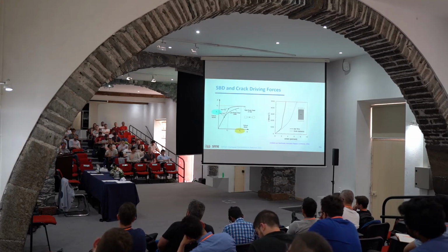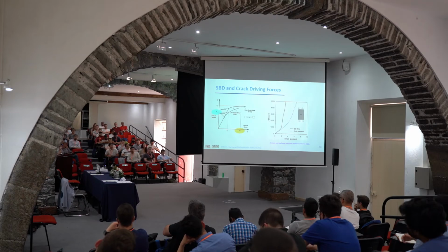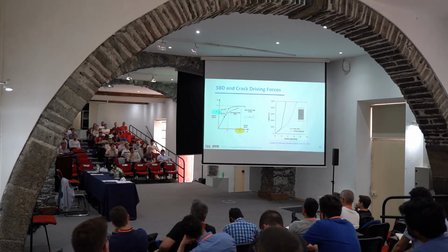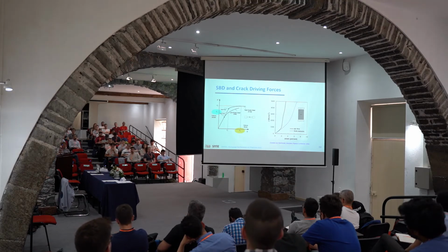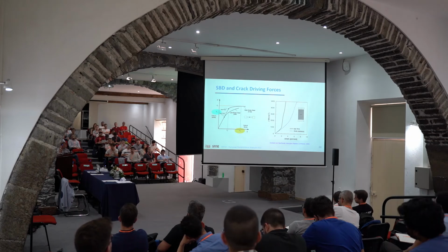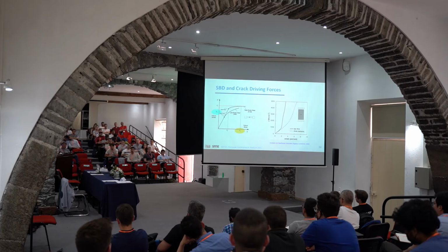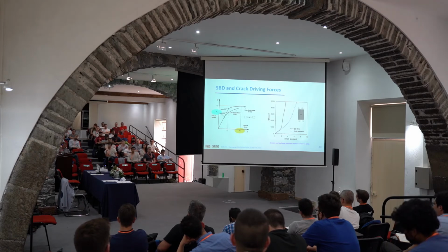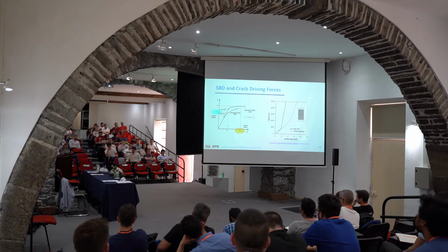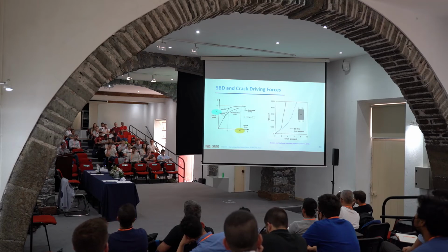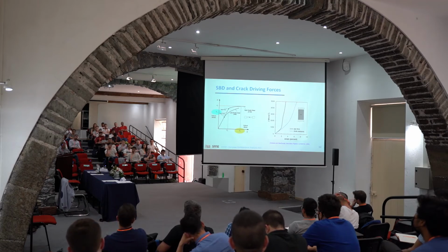So for high strength steel, the mobility is lower. So what happens is, after you reach the yield point, you deform the material with much less stress. That's the meaning of hardening from the fracture mechanics perspective. We're not interested in what happens in the lattice structure, if it's pile up of any kind of defects, doesn't matter. What matters is that the plastic flow behavior will impact the fracture mechanics assessment. So that's why for this class of new materials we should be using strain-based assessment, not stress-based assessment.